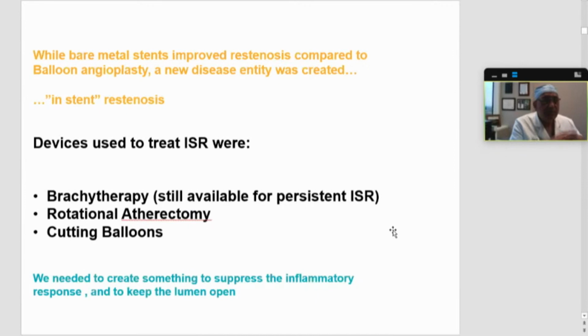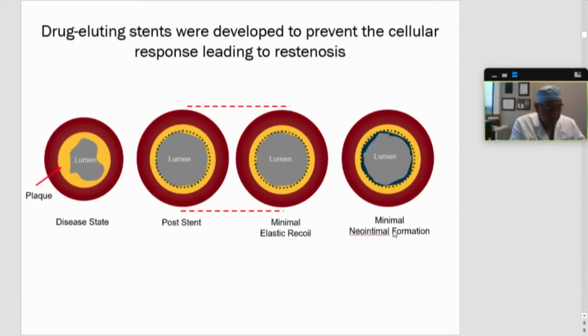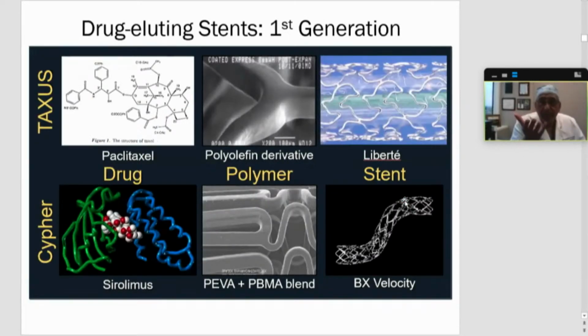So devices used to treat in-stent restenosis were brachytherapy, which is still available, and our institution does that, rotational atherectomy, cutting balloons, but we needed to create something to suppress the inflammatory response and to keep the lumen open. Remember, this was not as much cholesterol driven as much as scar tissue driven. And that's when we wanted to create this idea that, yes, you have a stenotic lesion, you put in a stent, and there is minimal elastic recoil, but also you want to prevent this further stenotic response, neointimal formation. So that led to the drug-eluting stents.